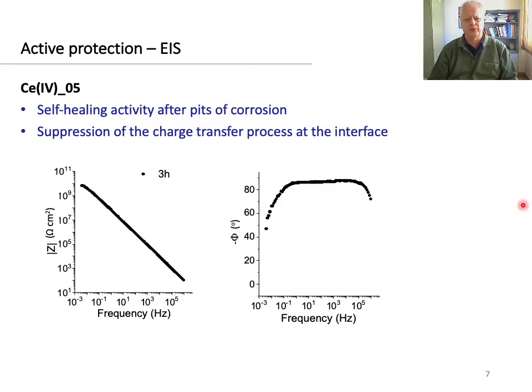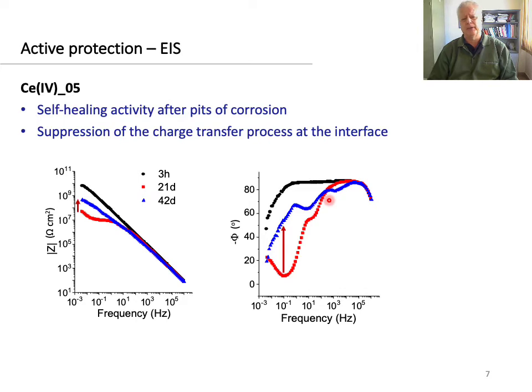Here we can observe the main changes in the EIS profile before and after failure. After 3 hours of immersion, a quasi-ideal capacitive behavior is observed over almost the entire frequency range, followed by a drop after 21 days due to local failure. However, after 42 days, a self-healing effect occurs, recovering the impedance modulus by one order of magnitude.